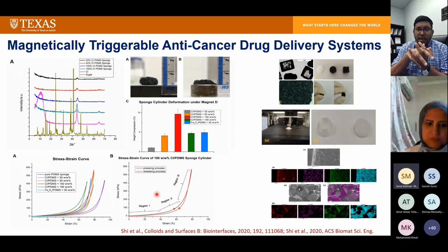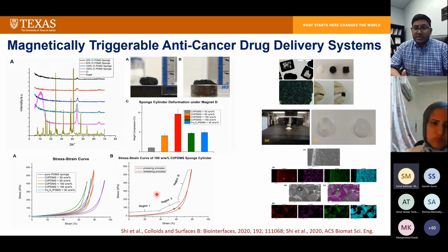So that is just to show how a magnetically triggerable anti-cancer drug delivery system can be developed by using 3D printing strategy. So here we developed a macroporous sponge, PDMS-based sponge loaded with magnetically triggerable particles, and then we loaded anti-cancer drug into the sponge, and we used actually 5-fluorouracil as the model anti-cancer drug. And the idea was basically to use magnetic field as a triggering factor for kind of like squeezing that macroporous sponge to release the drug on demand. So that can be an ideal solution for long-term treatment or long-term delivery of chemotherapeutic candidates in the future.